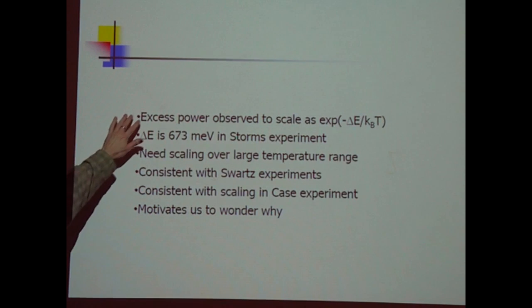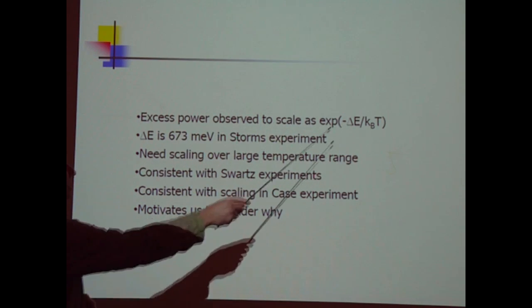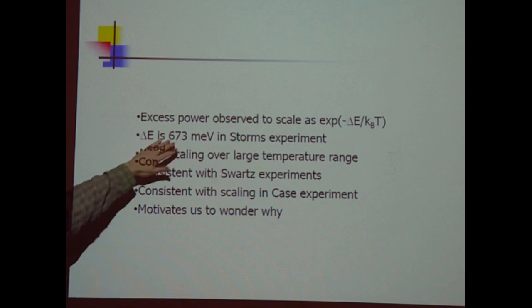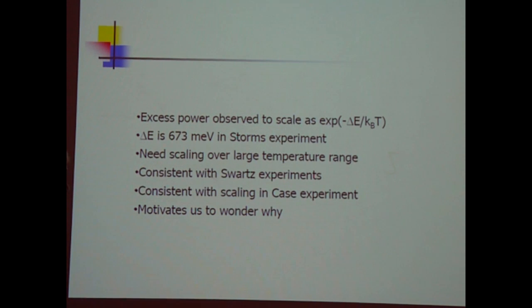So excess power in a number of experiments was found to scale in this way. Storms got 673 millivolts. Mitchell got 715 millivolts, basically a very similar number. Case got close to 700 millivolts for temperature scaling at much higher temperature. So we would like some systematic data over a larger temperature range to really be sure. I mean, the temperature range isn't enough in this, but there's enough here to motivate us to wonder why the excess heat varies with temperature.